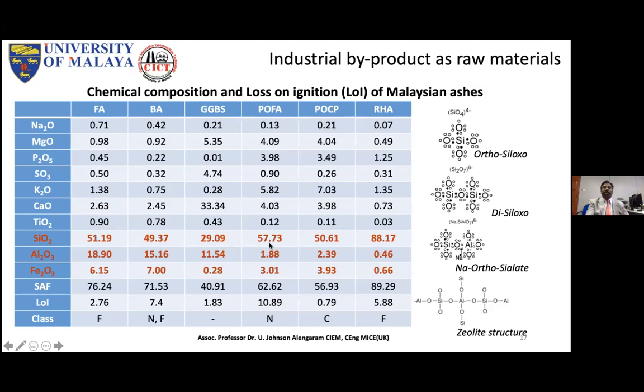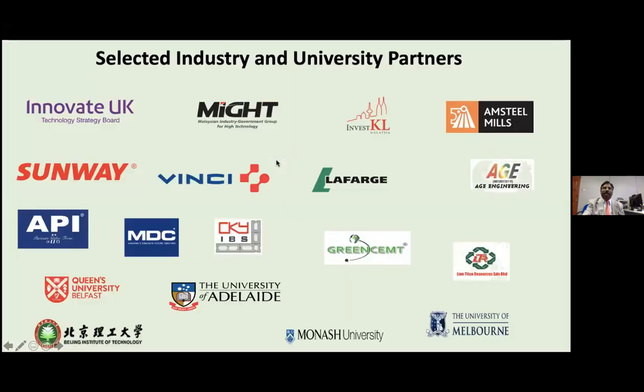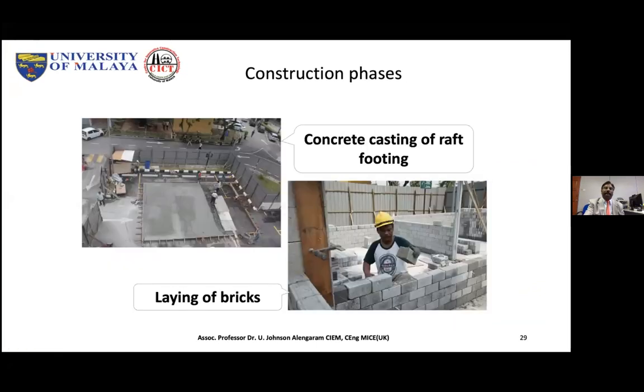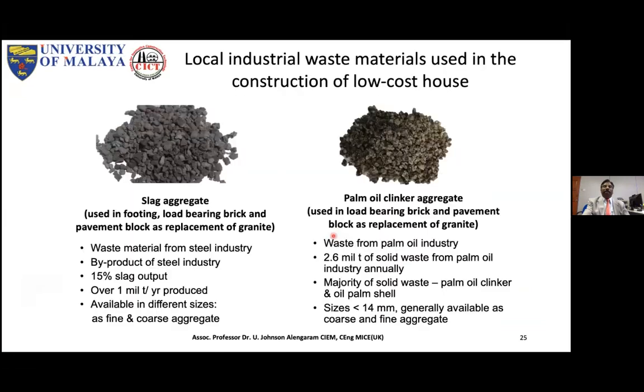So this can be used as a filler. The pozzolanic activity is not much, but we can use it as a filler or even as a pozzolan to a certain extent. We have done it. So this is the palm oil clinker as a powder, meaning I can use it as cement replacement. I mentioned during the presentation, 15% used as cement replacement. Say in this place, you see my slide, 15% means only 85% cement, but 15% of this powder. We can go up to 30%. It's no issue because, if you see the chemical property, and because I have time, I'm explaining more.